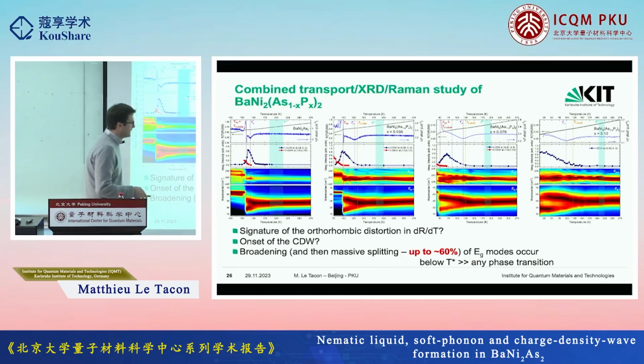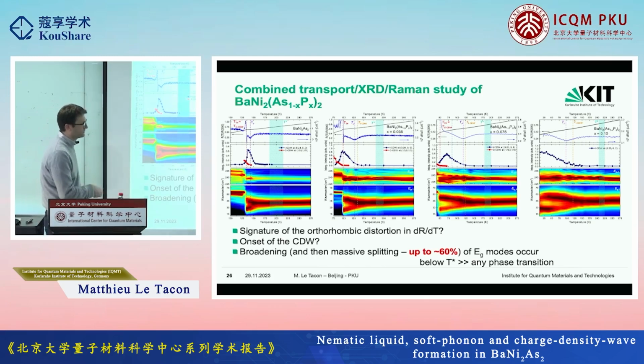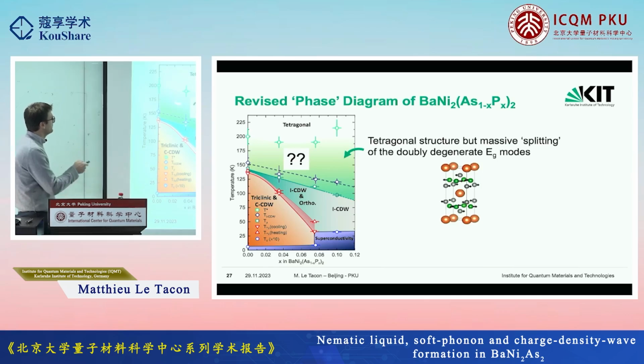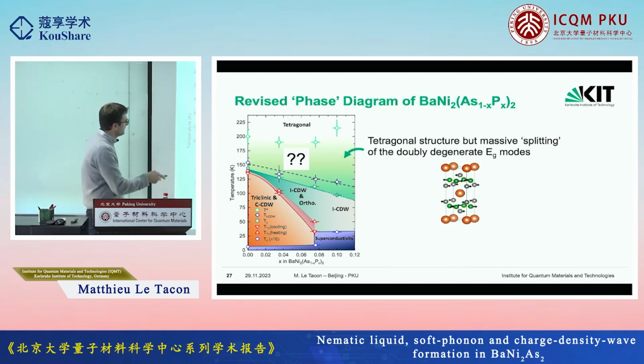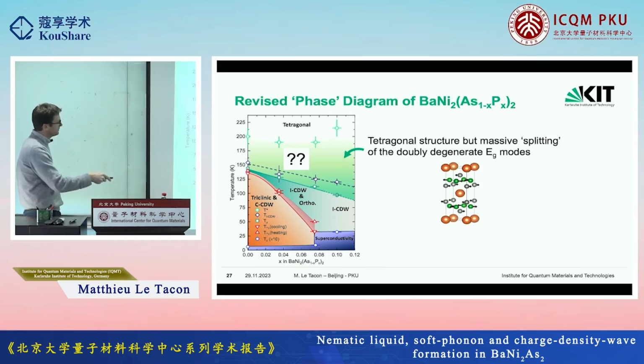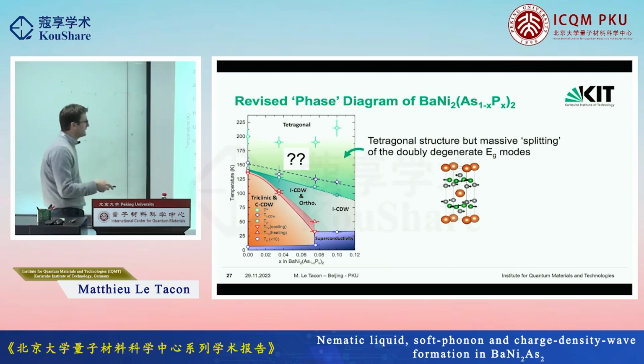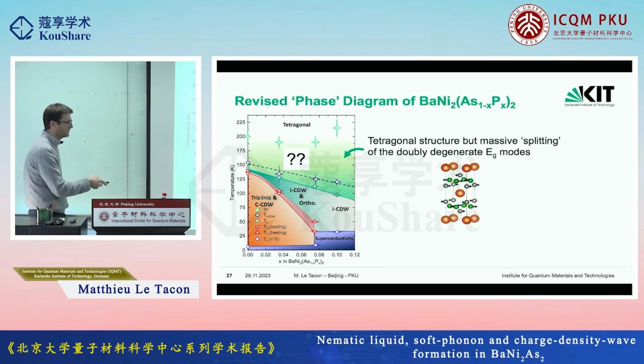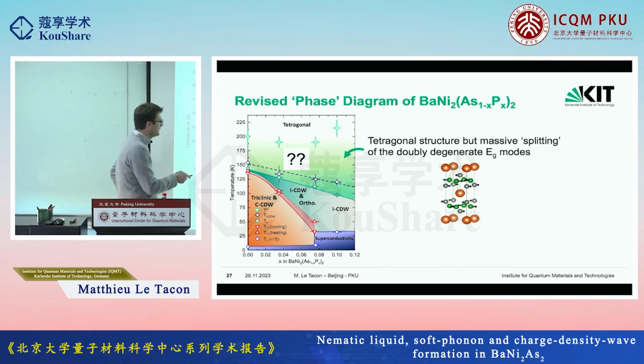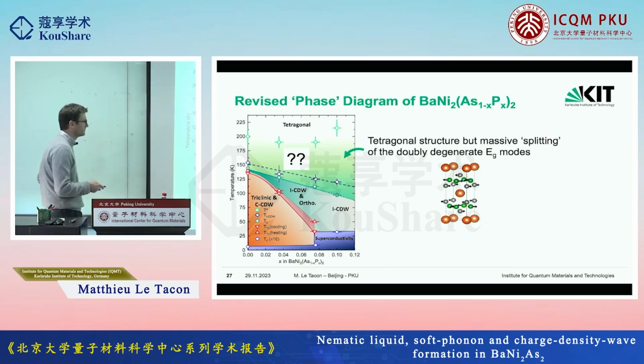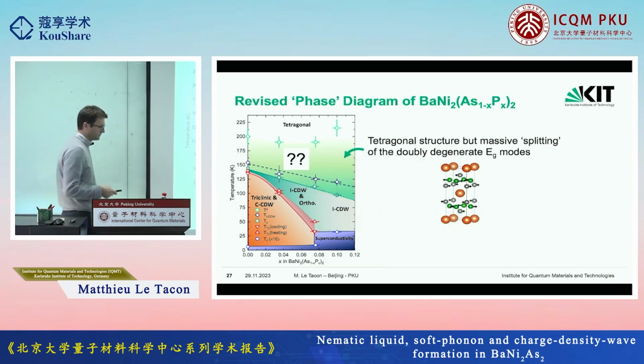So, and again, this onsets well above any of the phase transition that we can see with conventional thermodynamic method. So I put this on this phase diagram here, and that's the onset temperature of the splitting, and it has this weird thing. This is where the incommensurate charge density wave is detected as an order. This is where we see the orthorhombic distortion. And actually, in that 10% compound, we don't even see an orthorhombic distortion. So we see no difference between A and B. We see a small thing happening along the c-axis. I'm not going to say too much about it, but pretty much this guy here is completely tetragonal, yet you have this large splitting of the phonons.